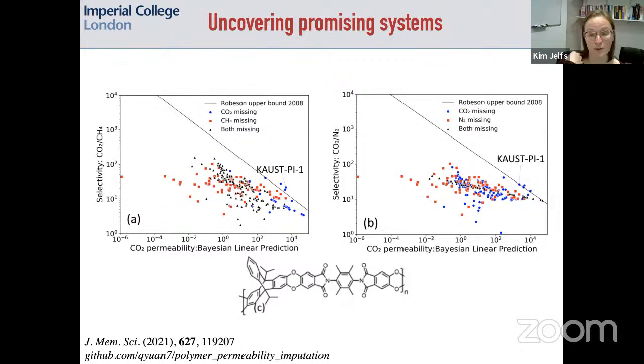So if we look at the two plots here, I guess this crowd is familiar with what we're trying to do. We're trying to break these trade-offs between selectivity and permeability to find better systems. In these plots, the left-hand one is for CO2 against methane and the other is for CO2 against nitrogen. All of these points are new ones where we can now do this comparison because we've filled in the missing points. The blue points are where the CO2 was missing, the red is where the methane was missing, and the black is where both were missing.